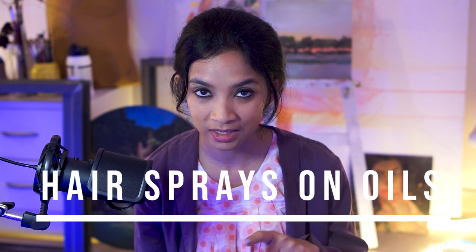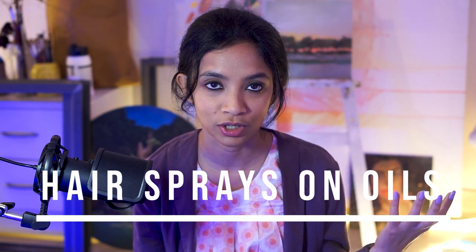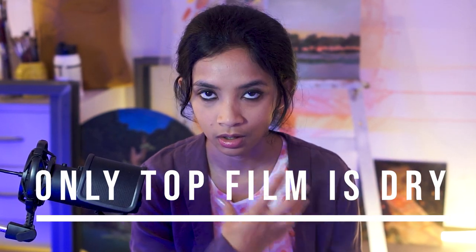Now I will tell you what not to do. Some people have spoken about using hair sprays. When you put a hair spray on the painting, it makes a film. It does not make the painting dry faster — what it actually does is make a film on top of the oils on your canvas. That film is dry, but underneath it the oil paints are not dry. That will result in cracking. The hair spray is not the same medium as the oils in oil paintings, and hence it will result in cracking or deterioration. So do not use hair spray to speed up the drying process.